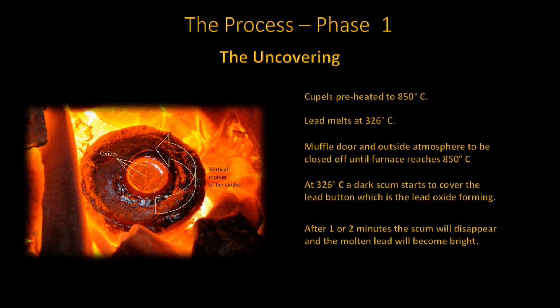The furnace temperature will cool down when the loading of the buttons into the Cupels is carried out. To allow the temperature to once again reach the required 850 degrees centigrade, the muffle door must remain closed. This takes about 10 minutes. The disappearance of the scum is called the uncovering, or sometimes termed the opening up of the lead button.